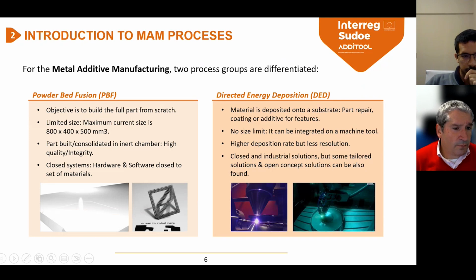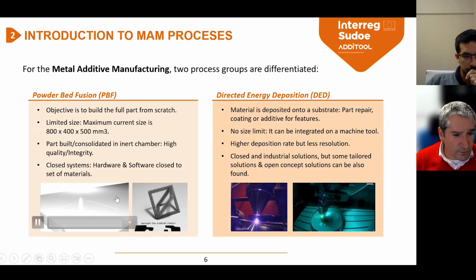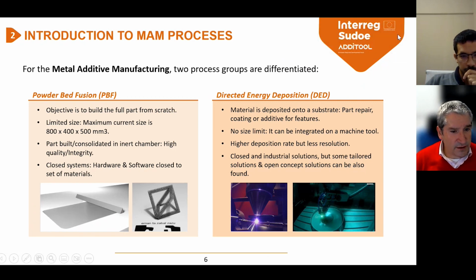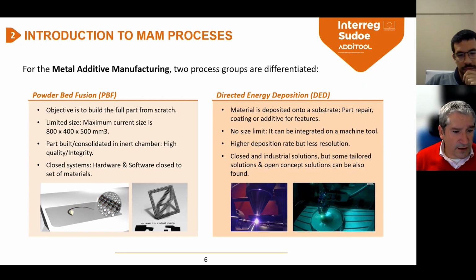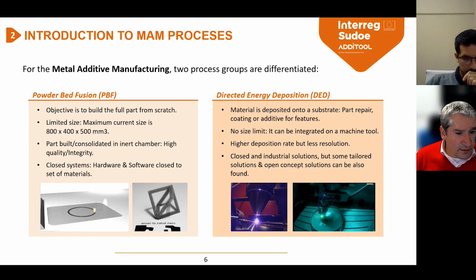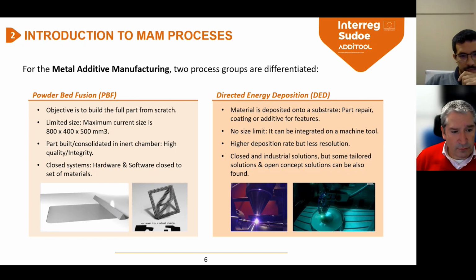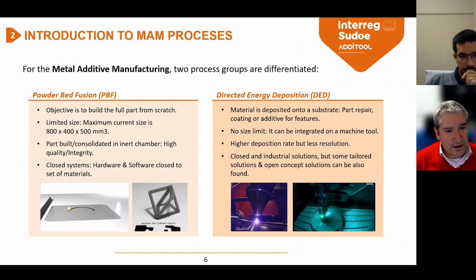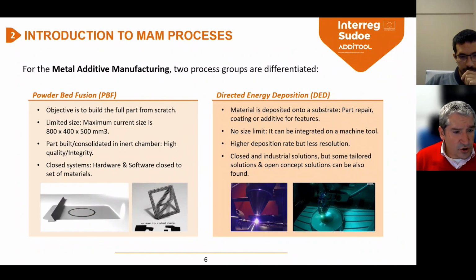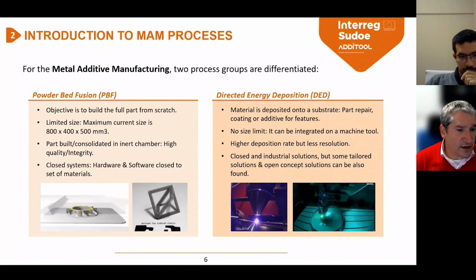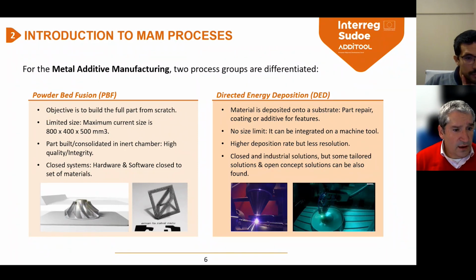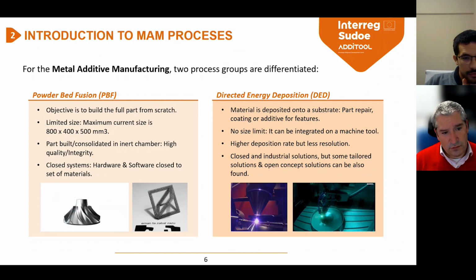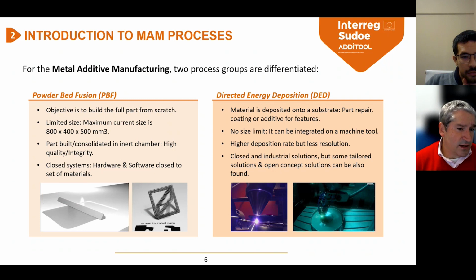Probably you will know them, but if not, in short, powder bed fusion is used for building parts from scratch, from zero. So the idea is to go layer by layer to build a full part. The process is carried out in an inert gas chamber, usually argon. So here we have a first limitation of the process. Since we have to insert the part into an inert chamber, the part size is limited.